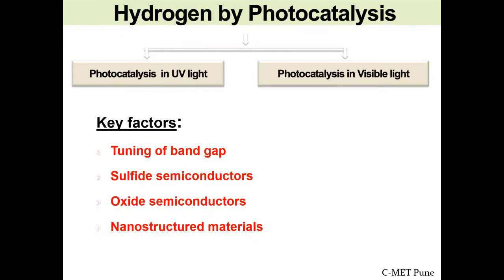So we synthesize sulfide semiconductors, oxide semiconductors, or dope with something, like TiO2 doped with nitrogen. We can tune the TiO2 band gap into the visible region. So that we do.